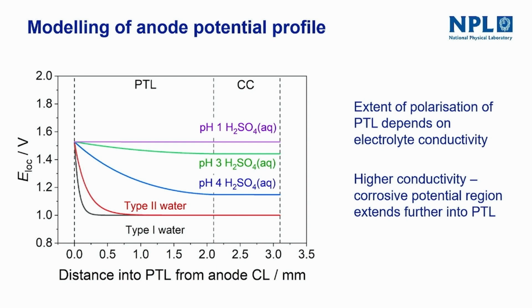As you increase the conductivity of the water, then you do see that potential transmitted all the way to the bipolar plate. But in a real operating electrolyzer where you have an ion exchange resin, the conductivity of the water is kept very low. So these are just very unrealistic conditions to demonstrate the throwing power analogy.